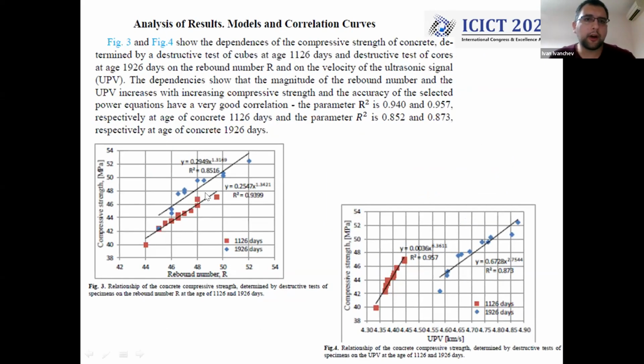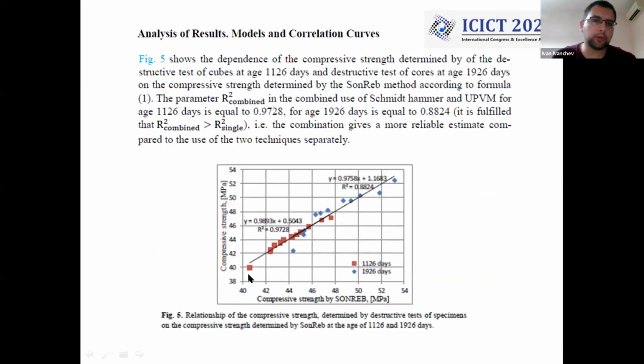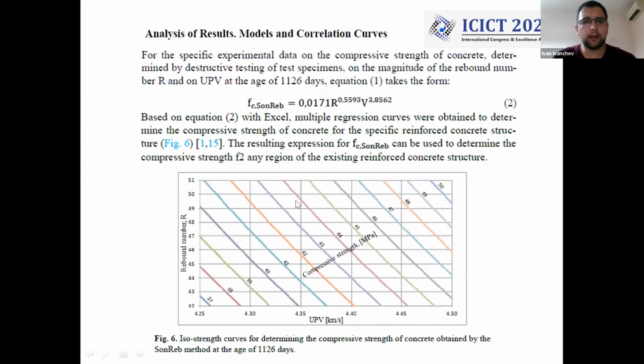So there are curves which are from the analytical models. You can see the relation of compressive strength via the rebound number R, or compressive strength via the ultrasonic pulse velocity. The next thing which I want to show is another curve, which is compressive strength by the SonReb method with compressive strength which is determined with cubes. You can see that the R square coefficient is close to 1, so we have a very good fit.